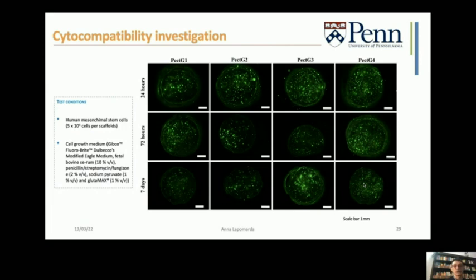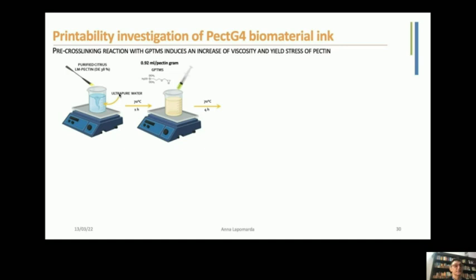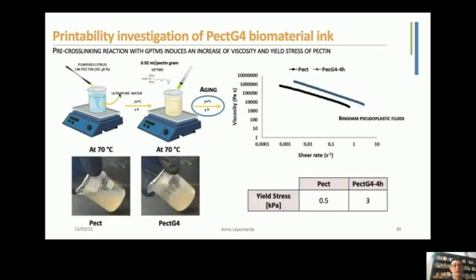We tested this scaffold with human mesenchymal stem cells, in collaboration with the University of Pennsylvania, with Professor Gottardi, and we can see that the biomaterial was biocompatible because all the scaffold was completely filled by the cells. So at this moment, we are trying to optimize the use of pectin in order to produce the bioink. So what we did, we created our solution with pectin, adding GPTMS inside. We left it to react for 4 hours, and then we analyzed the viscosity